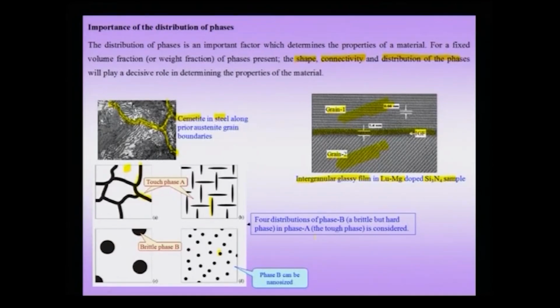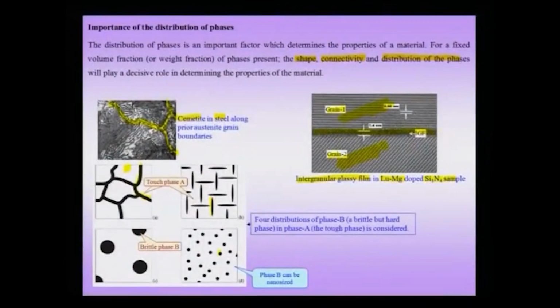Now, suppose the silicon nitride sample is loaded, sometimes in impact, then it could so happen that the cracks may propagate along this glassy phase rather than propagating through the grain, and therefore, this material may have a characteristic which is brittle as compared to if the crack was propagating in a transgranular mode.